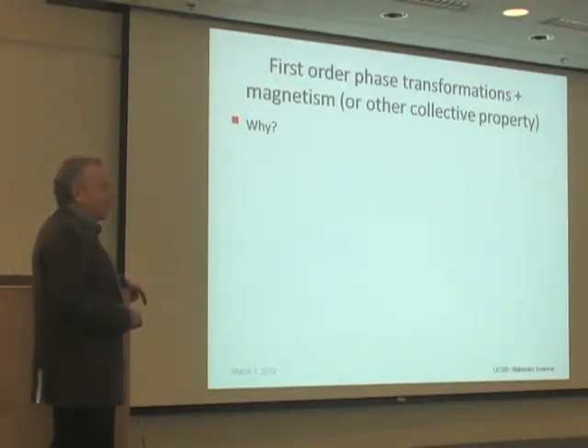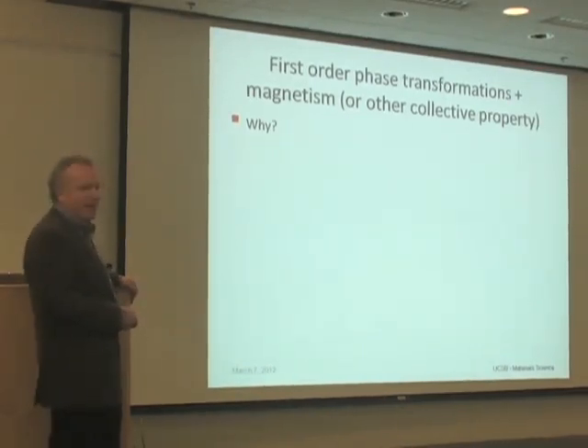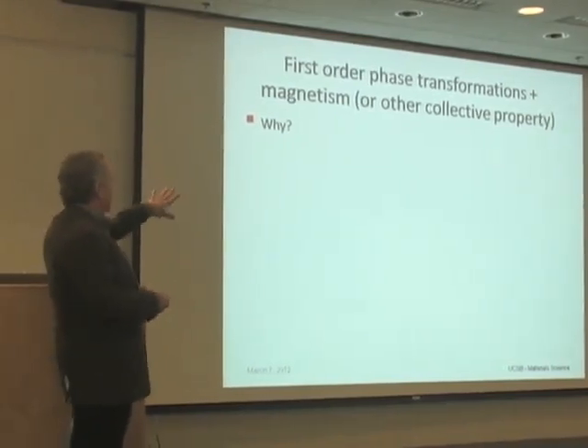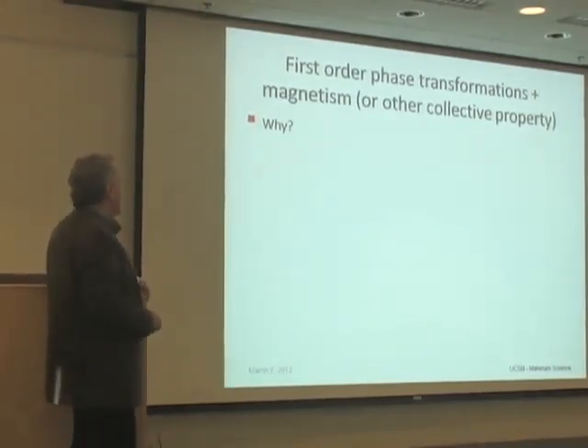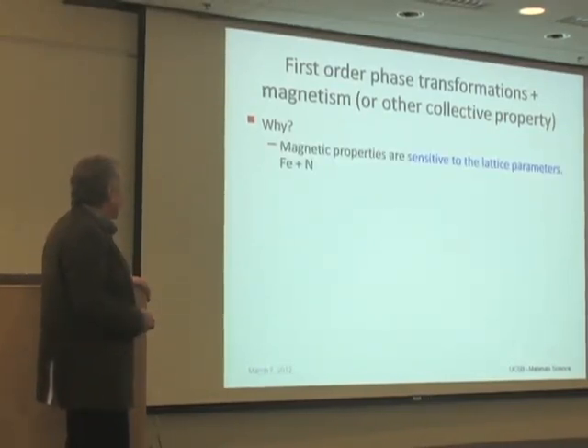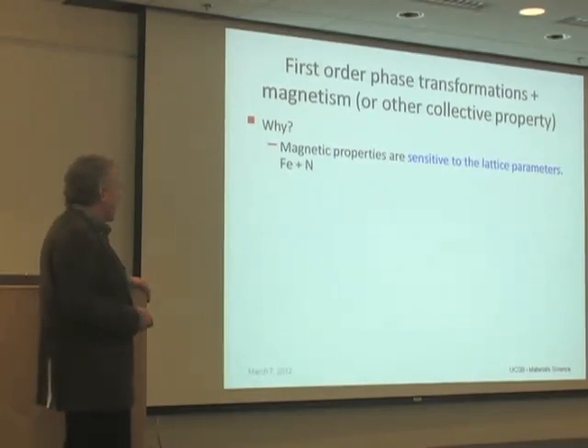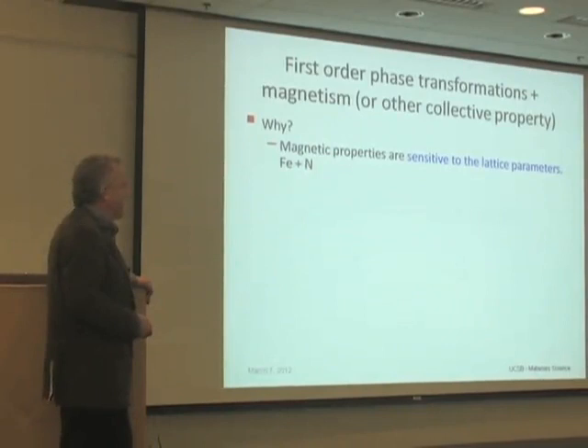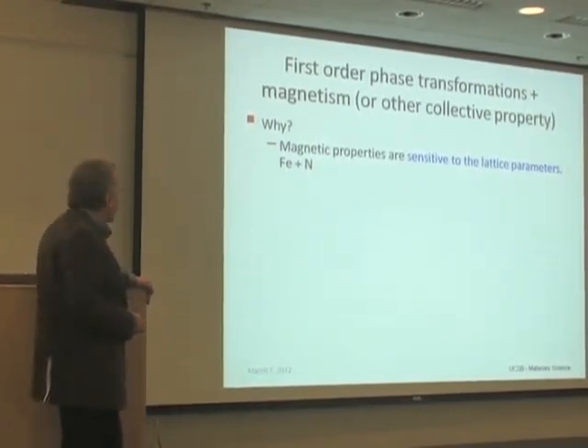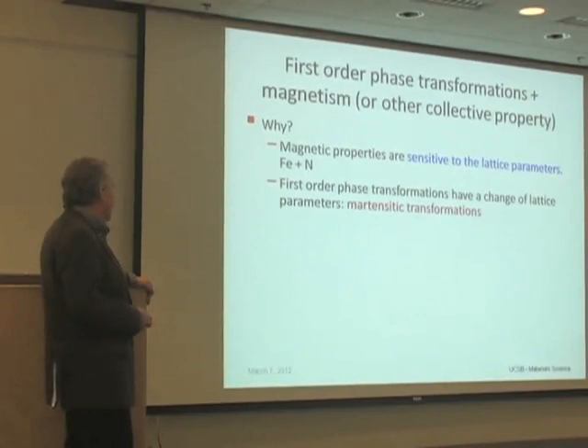relies on first-order phase transformations in solids. So one crystalline phase to another, sometimes we call those martensitic phase transformations, and also magnetism. But you could also think of other properties, and I'll come back to that later. The reason for this way of thinking is that magnetic properties are generically sensitive to the lattice parameters of the material. The classic example, which is also controversial, is the diffusion of nitrogen into iron, which expands the lattice and improves the magnetic properties. And first-order phase transformations have a change of lattice parameters. That's the type I'll look at.